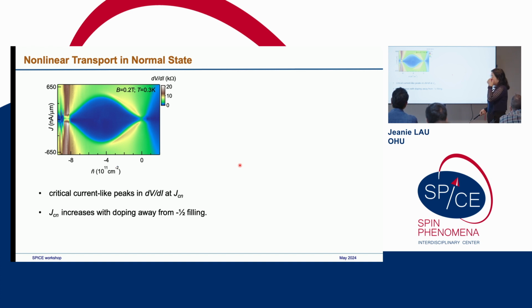Okay, so now we're going to do something a little bit unusual, which has not been done so much, which is nonlinear transport, meaning we apply a bias voltage. This graph plots differential resistance dV/dI as a function of current density and charge density. Again, charge density we measure from the so-called half filling point, meaning where we have 2 electrons per unit cell is 0, because of this Dirac revival story. And we apply a small magnetic field, 0.2 Tesla, to suppress superconductivity, so this is in the normal state.